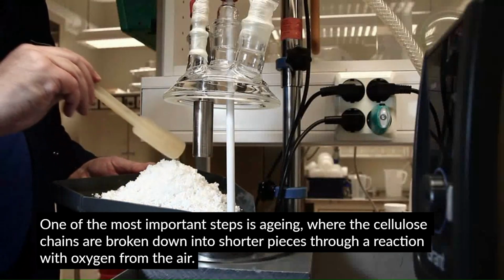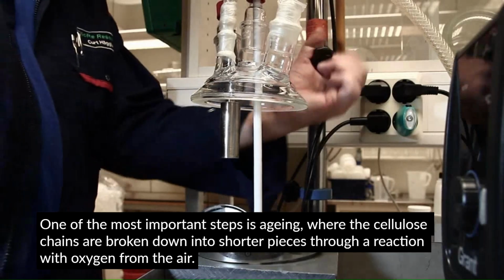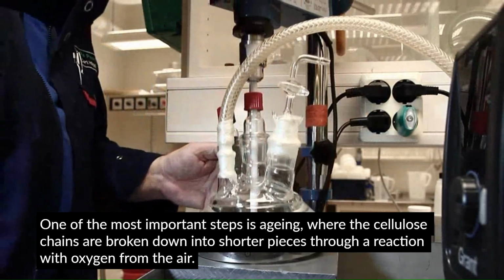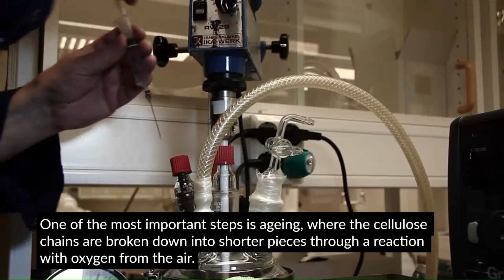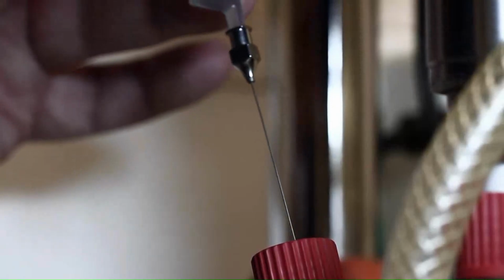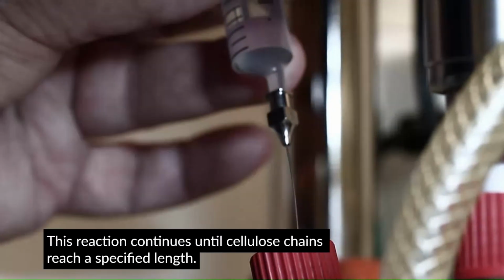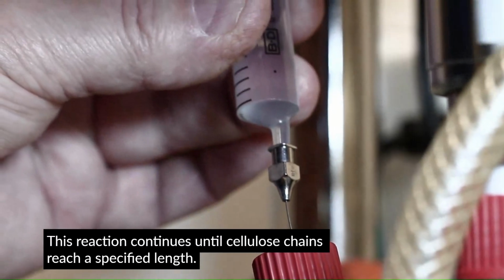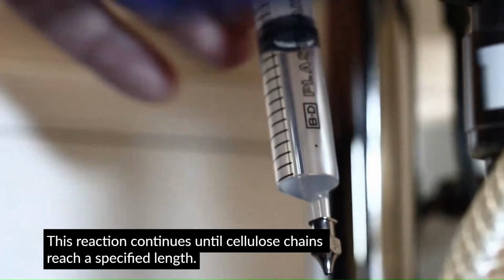One of the most important steps is aging, where the cellulose chains are broken down into shorter pieces through a reaction with oxygen from the air. This reaction continues until cellulose chains reach a specified length.